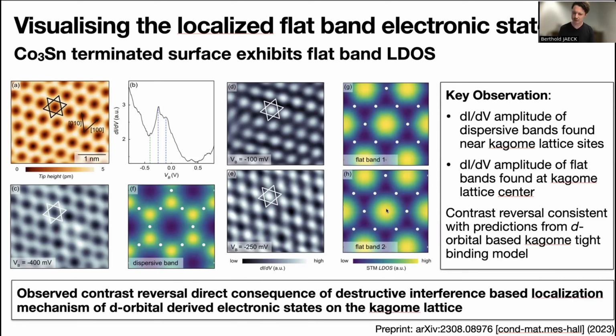More broadly, and I think why this is such an interesting observation, is that this contrast reversal, or the strong amplitude of the spectral weight of the Kagome flatband at the lattice center, is a direct consequence of the destructive interference-based localization mechanism here. And by virtue of this contrast reversal, which in fact is quite unique to d-orbital derived flatbands, we can essentially distinguish now this Kagome flatband density of states from other states, such as dispersive states we showed here, but also simply maximally localized orbitals or surface resonances that, in principle, also could show a somewhat localized structure at a surface in STM measurements.